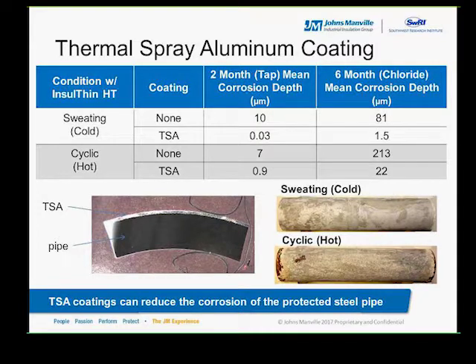The last corrosion-based analysis that we conducted compared the impact of TSA, or thermal spray aluminum coatings, using the NACE TG516 test protocol. So we only looked at this with Insulthin that was coated with TSA coatings and applied to the pipe before installing the insulation, and not the silica aerogel blanket. So we can see on the bottom left-hand corner picture is a nice TSA coating on a section of the pipe from a sample of the tested specimen.